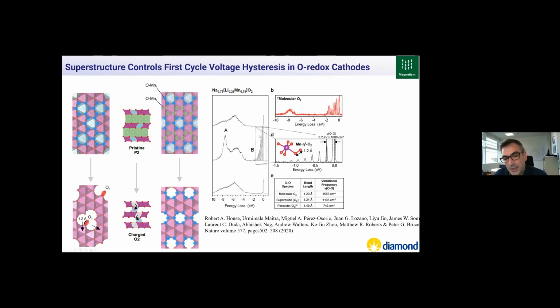But these beamlines essentially gave access. So with RIXS, you can probe the material, doing some sort of vibrational spectroscopy to look at the formation of molecular oxygen, or something very similar to molecular oxygen, extremely weakly bound to defects that are created in the solid during the first hysteresis cycle. And you can use RIXS to quantify the vibrational modes that you have in this weakly bound oxygen. So this is something quite interesting, and a new application of RIXS, which has also been done by other groups and other synchrotrons.